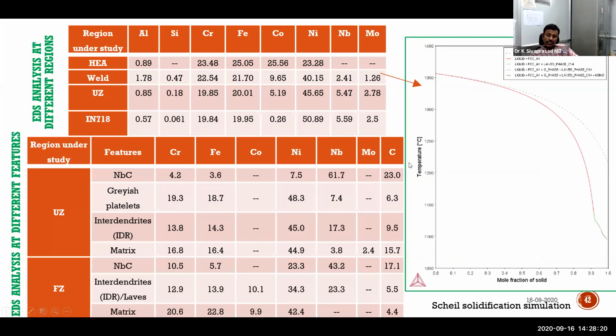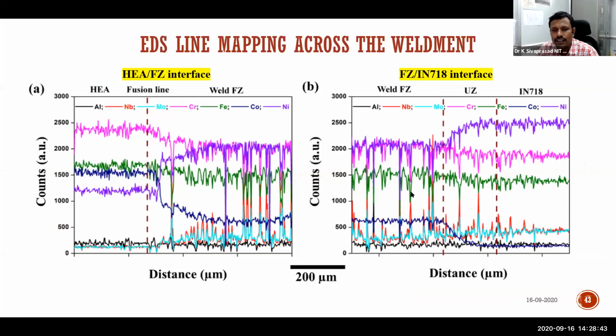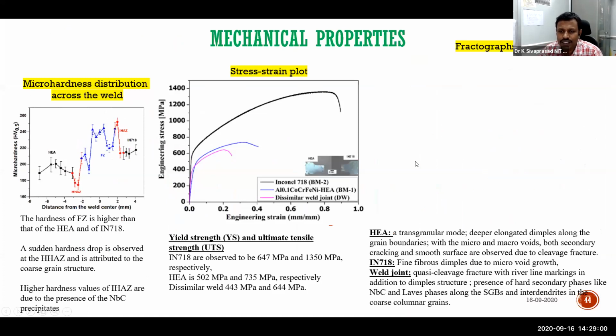Again, the CALPHAD approach, because we have to confirm that there are no other undesirable carbides forming. Yes, here also M23C6 kind of carbides are not forming. But here the curve is slightly closer, with some minor carbides. So if you are not standardizing the welding process, you may end up with undesirable carbides. It's a cautious thing that we have to keep in mind. And here also elemental distribution is uniform. The many dips and fluctuations here and there at particular intervals are associated with Laves phase formation in the weld fusion zone, in Inconel 718 especially. Again, here also we have seen that the dissimilar weld joint is comparable to that of HEA, definitely.